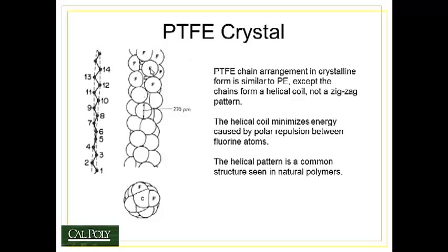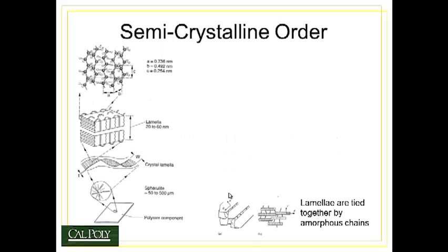Polytetrafluoroethylene, however, forms a slightly different molecule. Remember that polytetrafluoroethylene is very similar to polyethylene — all you're doing is replacing the hydrogen atoms with fluorine atoms. But because of the large electronegative charge on the fluorine atoms, they repel one another, and this causes a slight helical rotation of the polytetrafluoroethylene molecule. As you look down the side of the chain, you get a gradual rotation of the atoms. It turns out this helical pattern is very common in natural polymers, which tend to have more polarity than synthetic polymers.